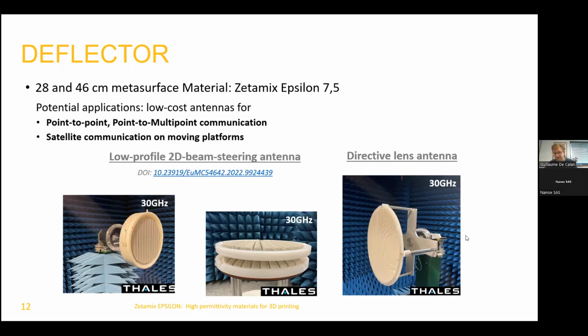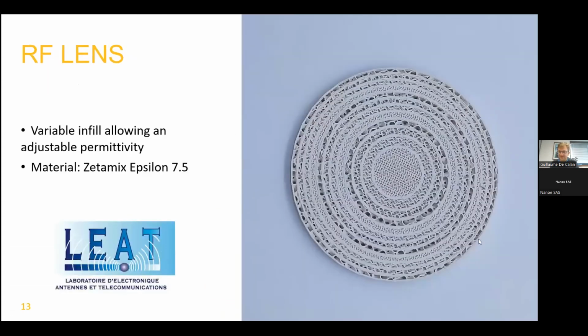So that's really the first application we started with. You can see that these parts are relatively big. That's one of the reasons why we went to a ceramic filled filament and not a ceramic material. We are printing at the moment parts of 28 centimeters, and the biggest one, which is on the right, is 46 centimeters wide, and we're working on printing bigger parts with the same kind of patterns. So that was the first application with Thales, and then we started looking for other partners.